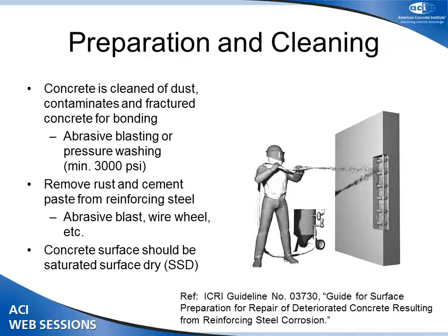And we want to make sure we remove the cement paste with any residual chlorides so that the bars are clean and that the material can bond well to the bar as well. And then finally, most common, you're going to use a saturated surface dry condition for the concrete. So you've cleaned it, you've opened the pores.